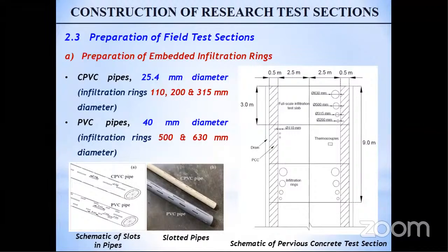Now, again, one of the objectives of the study was to investigate the infiltration rate through the surface layer of pervious concrete, while recommending the optimum size of the specimen that could be prepared in the laboratory to replicate the field infiltration rate, I should say. So in order to do so, we had some CPVC and PVC slotted pipes of diameters and dimensions as shown to you. Then these pipes were actually embedded within the infiltration rings, which were made of high density polyethylene material. And as presented on the schematic on the right side, about 3 slabs were chosen where the infiltration rings were placed of varying diameters, starting from 110 mm to up to 630 mm.